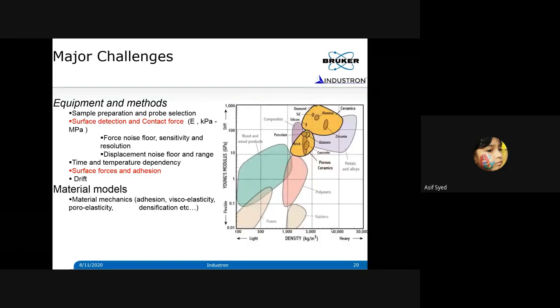So you have to redefine everything and reinvent and develop instrumentation that is capable of having high force sensitivity. As the materials become very soft, when you apply very small forces, the displacement will be very large, right? So not only do you have to have very high force sensitivity, the range of displacement should also be much higher than normally what you use for hard materials. So the probe should be able to measure large displacement jumps and large displacement excursions. So you have to have high force sensitivity and large displacement range, which means a different type of transducer needs to be designed.